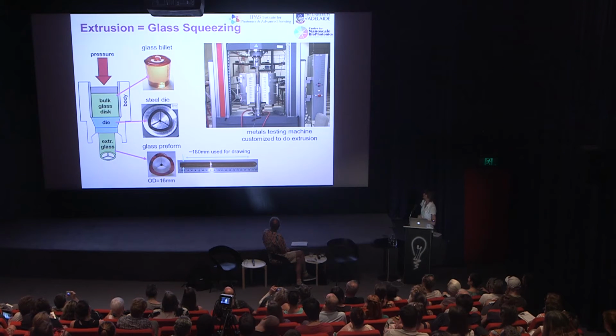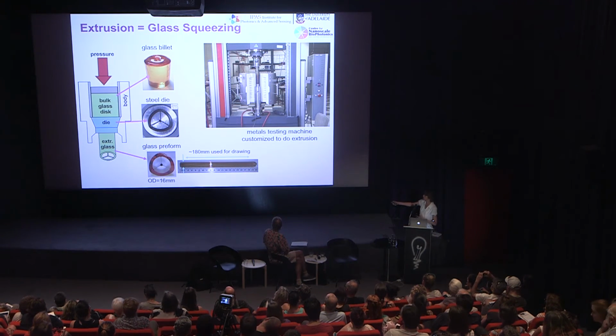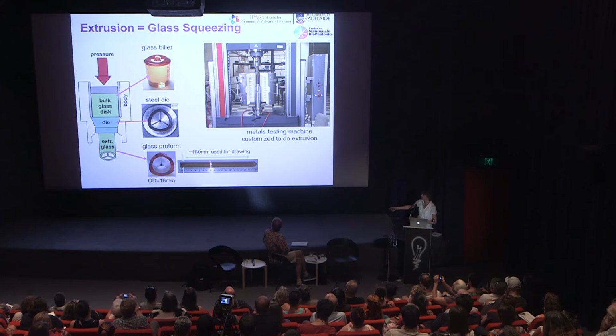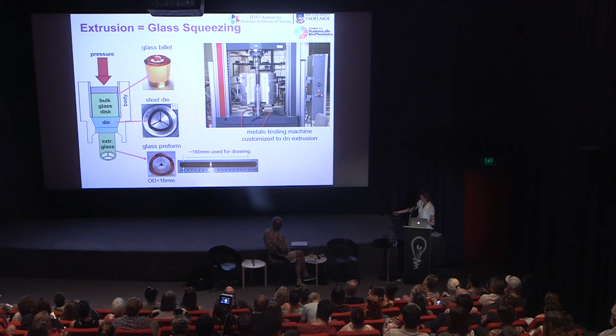the extrusion, which means we squeeze the glass billet at elevated temperature, when the glass is soft, through a metallic structure, a so-called extrusion die. Depending on the structure of the die exit, we sort of imprint the structure into the glass, and we obtain holes in the glass that run along the whole length of the preform.